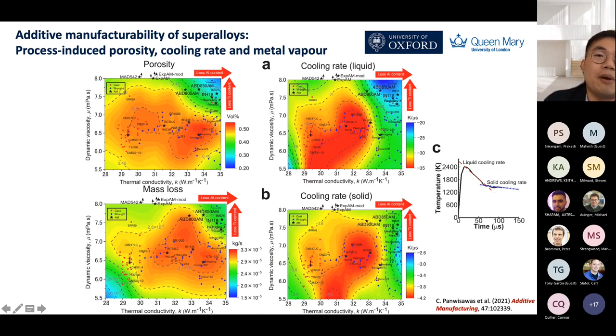And then you will see from this, nearly 35 calculations mapped in a contour, that the newly developed composition for additive manufacturing actually sits in the good printability region, where you have less porosity, less mass loss, and the cooling rate is not very extreme compared with some high gamma prime former superalloys.